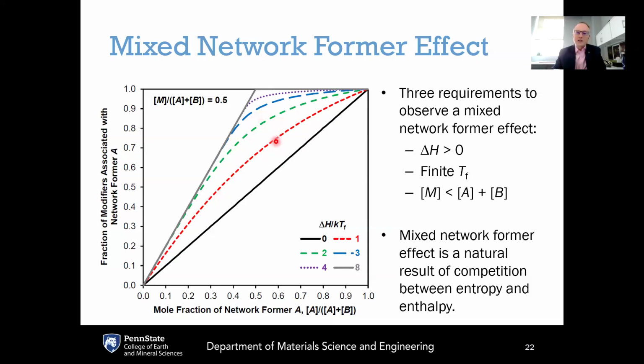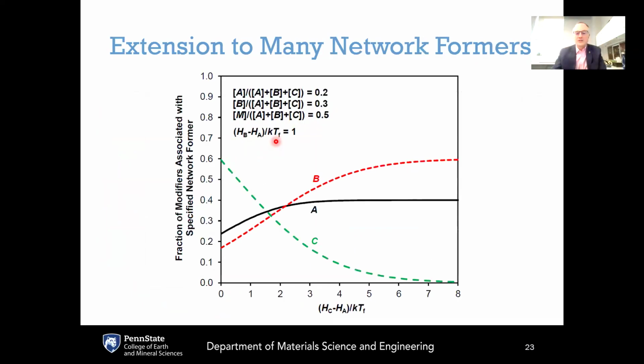And so that nonlinearity is the mixed network former effect, and that's naturally captured by this statistical mechanical treatment of the glass. It's really easy to extend this to the multivariate case. For example, what if you have three network formers, A, B, and C, and you've got a certain concentration of network modifiers M? What's the fraction of those modifiers that goes for each of those three network formers?